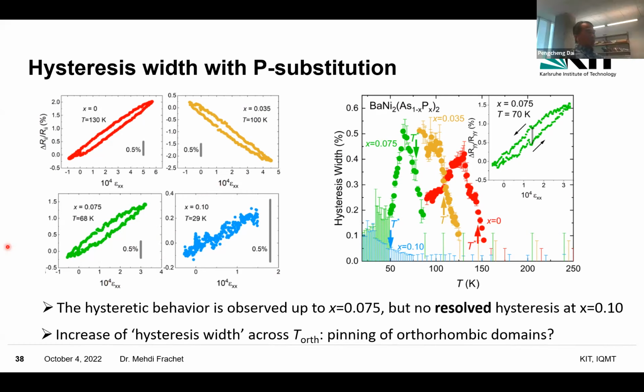Oh, there's one more question online, asking how do you define zero strain of the sample? This is from Zhaoyu Liu from, I guess, UW. Yeah, that's a good question. We cannot define the zero strain state in this experiment. We can try to estimate it from the thermal expansion of the piezo, but it's a difficult thing to do, especially just by gluing the sample to the piezo. You apply a bit of strain just by the drying of the glue, actually. What is important is that the resistance versus strain sweeps are still linear, so you are still in the linear response. That's the important part.